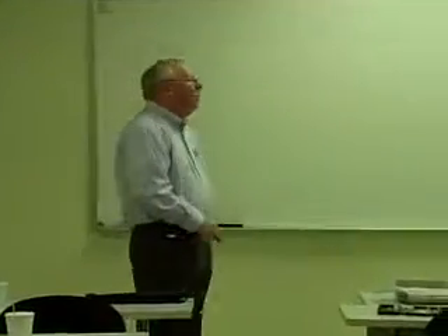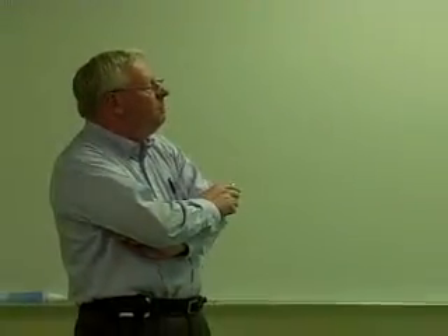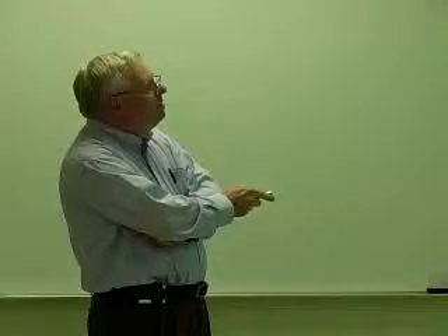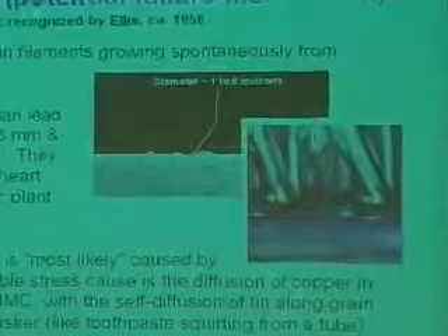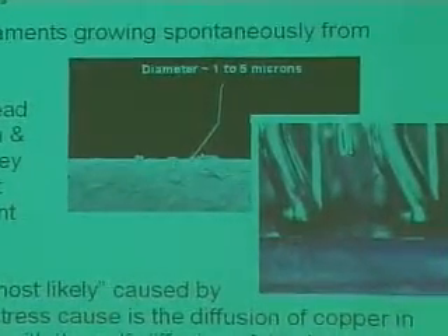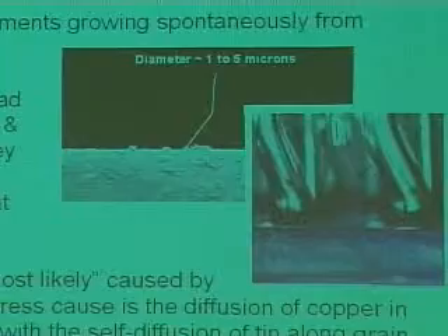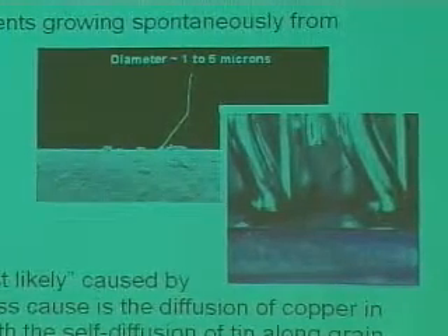Okay. Tin whiskers. And I know we have about 5 minutes left, so this is just about on the mark for timing. Tin whiskers are interesting because it turns out that you can get these very small fibers that grow out of tin. And you can see they're typically of the order of maybe 1 to 5 microns. They're pretty small. Some of the longest ones ever recorded were around 18 millimeters, but that's very rare. That's a world record, probably.